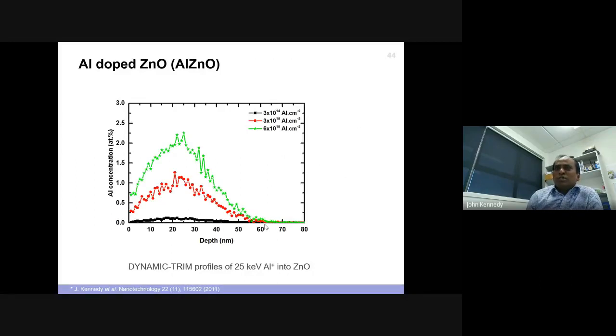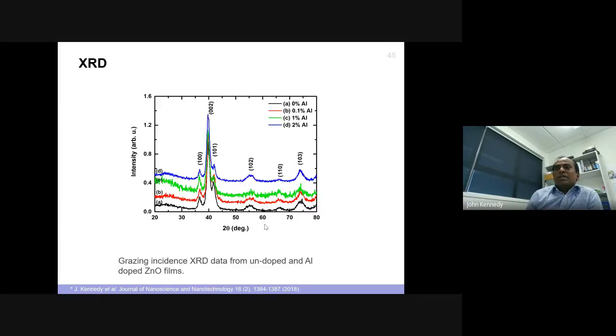So we doped 1 or 2% aluminum. We used our favorite technique called ion implantation, which is what I did during my PhD days, to dope aluminum into the zinc oxide thin film in this case. So what happened? Yes, the aluminum is inside the material. You can see by looking at the peak broadening the aluminum doping effect.